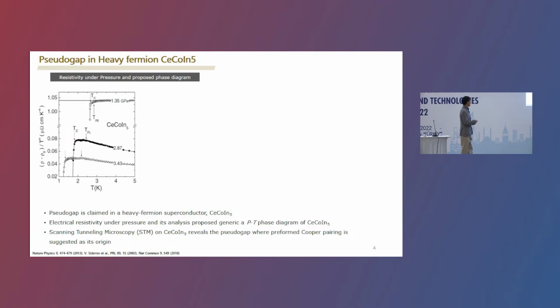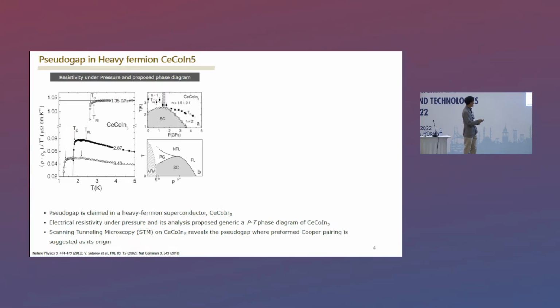And then at much higher pressures, this pseudogap-like phase transitioned to so-called Fermi liquid behavior, and he proposed a phase diagram like this one. So a dome of superconductivity centered around 1.5 GPa, and then pseudogap-like suppression, then Fermi liquid behavior.